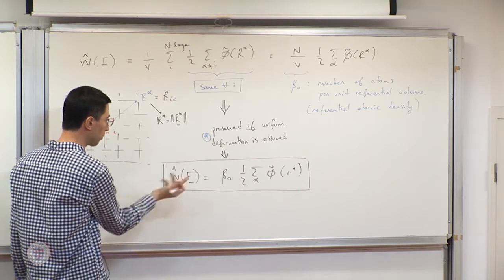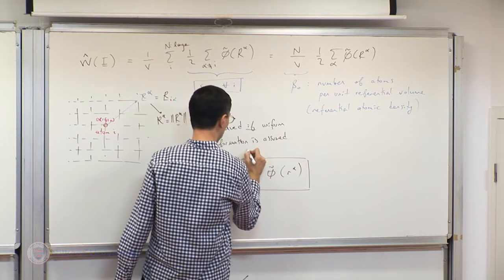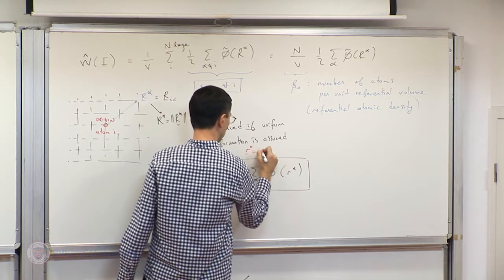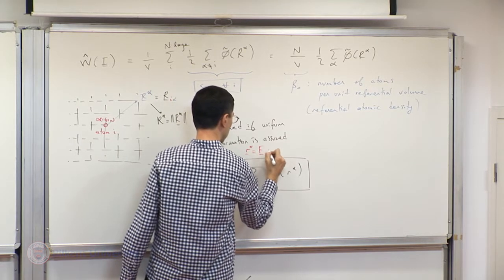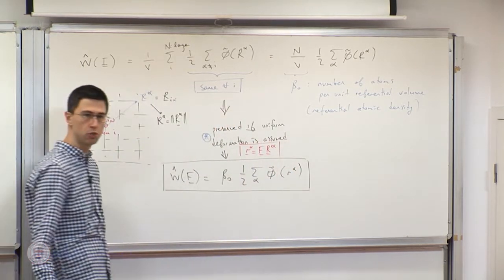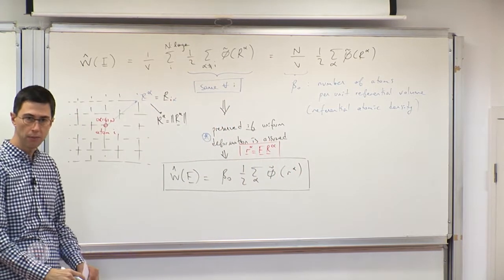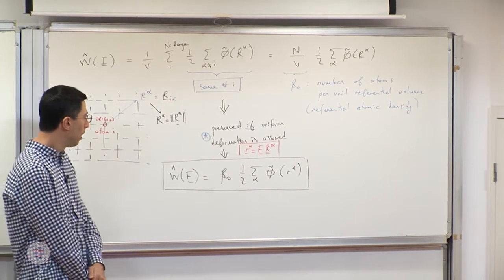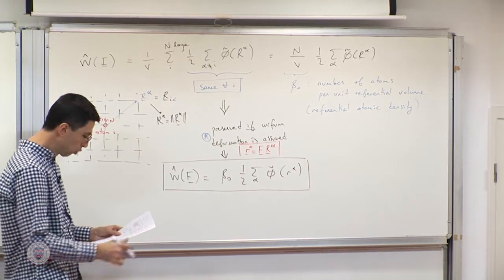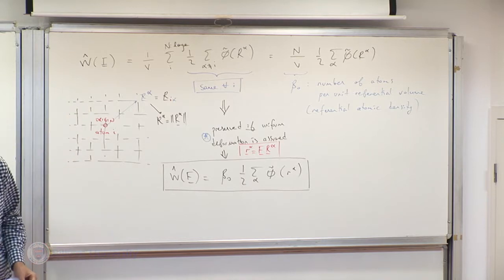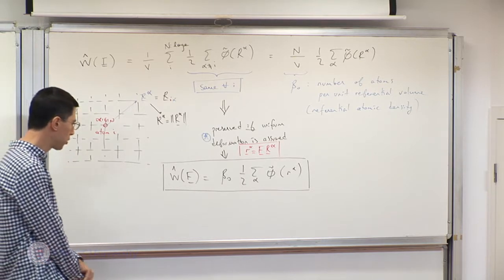It is important to invoke this uniformity in deformation through the Cauchy-Born hypothesis, which reads as stated. We now have an explicit and slightly simplified expression for the strain energy. We can take derivatives with respect to the deformation gradient and find the stress.